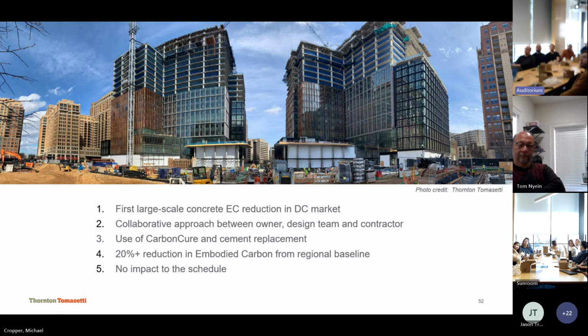So this project was really the first large scale concrete embodied carbon reduction in the DC market. So we achieved a little bit more than a 20% reduction in embodied carbon from the regional baseline. And that was mostly due to a collaborative approach between the entire team, and then an emphasis on performance specs, allowing mix designers to craft the best performing mixes that had lower embodied carbon.